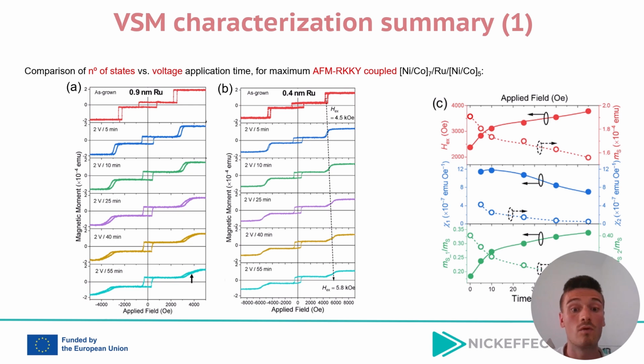To follow, this slide presents a complete VSM characterization of, in this case, antiferromagnetically RKKY coupled multilayers with 7 bottom ferromagnetic cobalt-nickel repetitions and 5 on top, focusing on how magnetic states evolve with voltage application time. Panels A and B show magnetization versus applied field loops for ruthenium thicknesses of 0.9 and 0.4 nanometers, respectively.